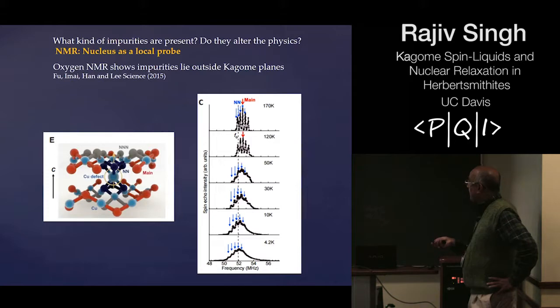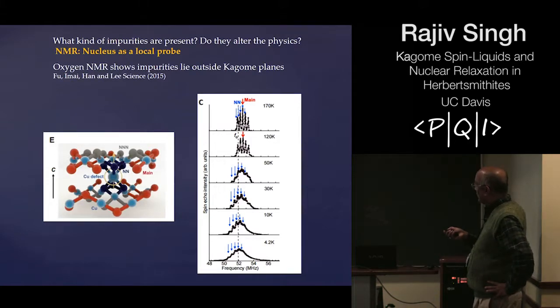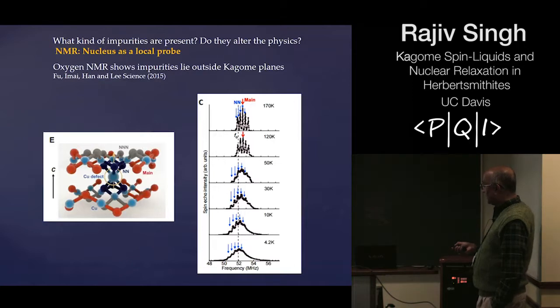Okay. So finally, the NMR experiment was done by Takashi Imai and his group, and this is also published in Science. The good thing about NMR is that it's a very local probe. The nucleus can act as a probe of the electronic system, basically the spin fluctuations very close to where the nucleus is. So even if we have impurities, let us say these blue guys are the copper spins. This is where a zinc spin would have been, but let us say there is a copper defect over here, and these blue guys are again the copper spins.